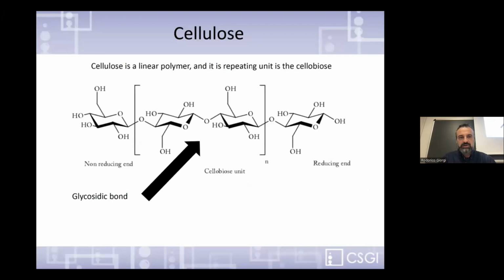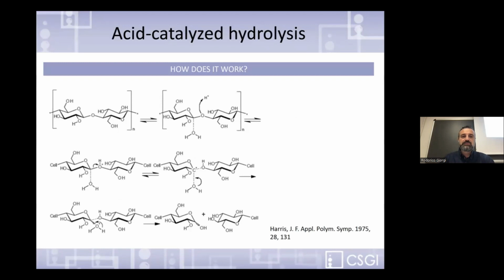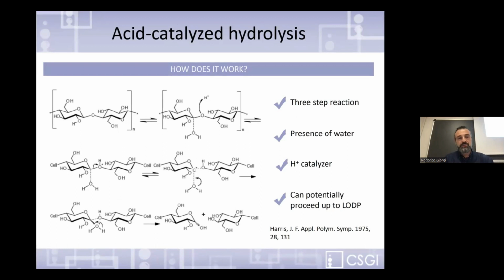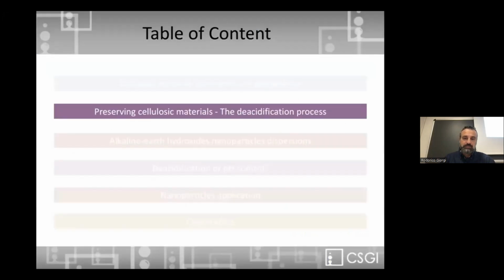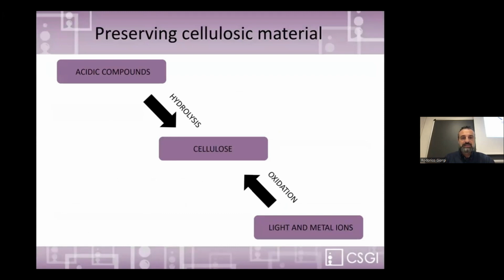The mechanical properties of paper come from the glycosidic bonds. And so the integrity of cellulose molecules is the key point to have durability of this material: books, archive materials, drawings, and whatever. And you know that the main menace for this type of bond is water in presence of hydrogen ion as a catalyzer of acidic hydrolysis of cellulose that can lead up to the leveling off DP, so a polymerization degree below 400, that means that paper crumbles with simple handling.